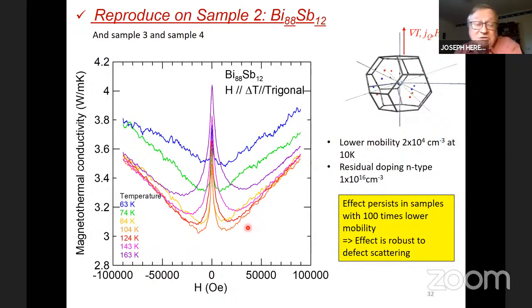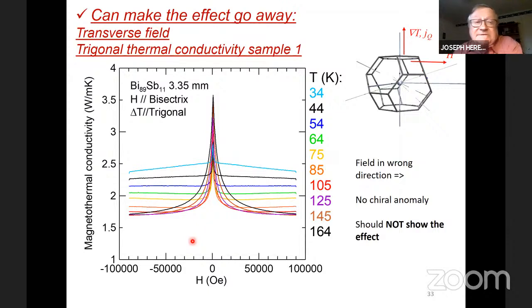And the temperature dependence is still there too. It is still a high temperature effect. These samples have a relatively lower mobility. So I claim that we have a good degree of robustness to defect scattering in the observations we have. And we have several such samples.